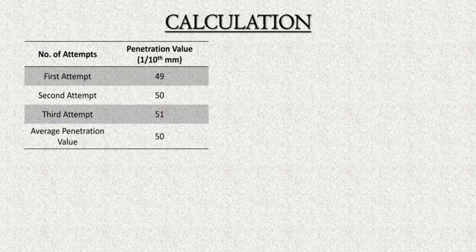Calculation: Penetration value. First value is 49, second value is 50, third value is 51. Average penetration value: 50.